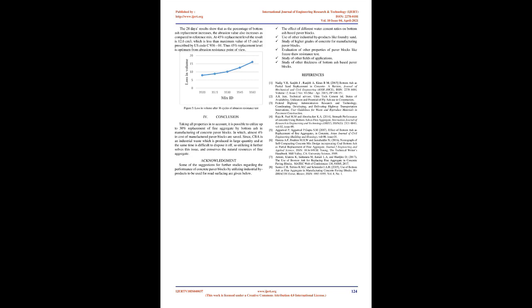At all levels of replacement of sand by CBA, water absorption increases with respect to the reference mix. The individual water absorption of specimens is within the code limit of less than 7%. Average water absorption at 30% replacement level is 5.81%, which is less than 6%, hence is optimum from a water absorption point of view. The 28-day results show that as the percentage of bottom ash replacement increases, the abrasion value also increases. At 45% replacement level the abrasion result is 12.6 cm³, which is less than the maximum value of 15 cm³ prescribed by ASTM C936-01. Thus, 45% replacement level is optimum from an abrasion resistance point of view.